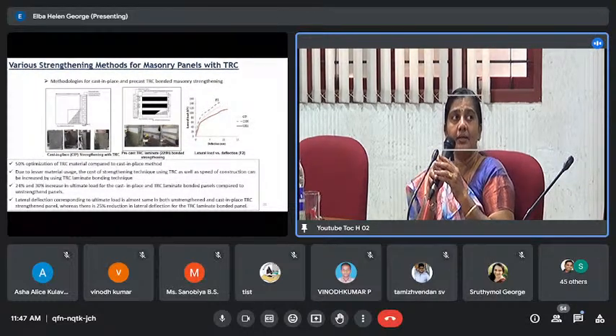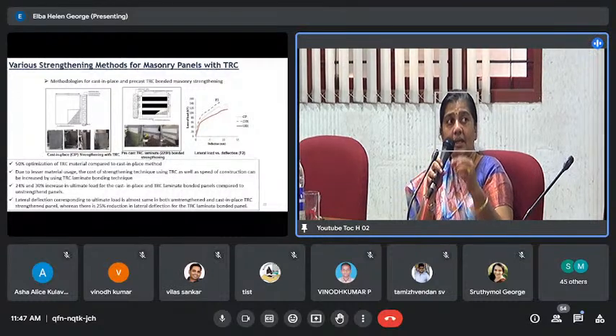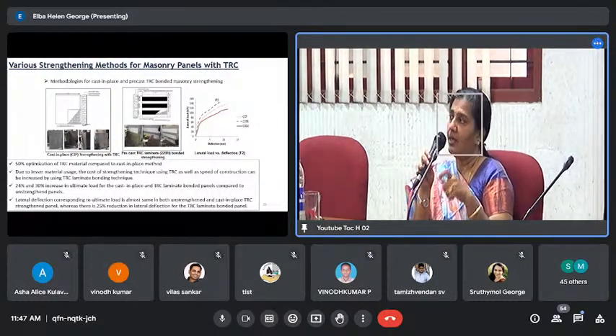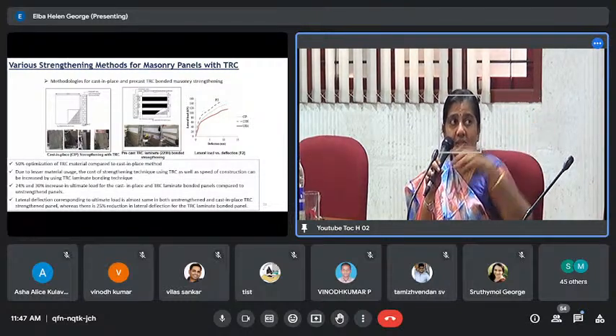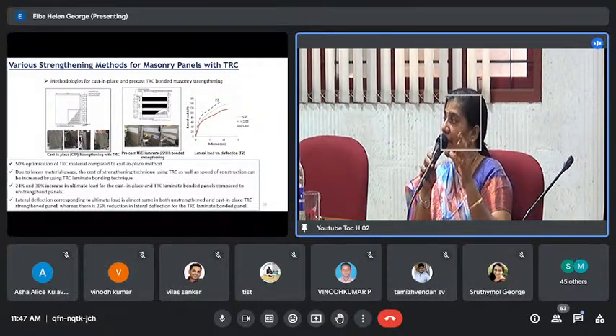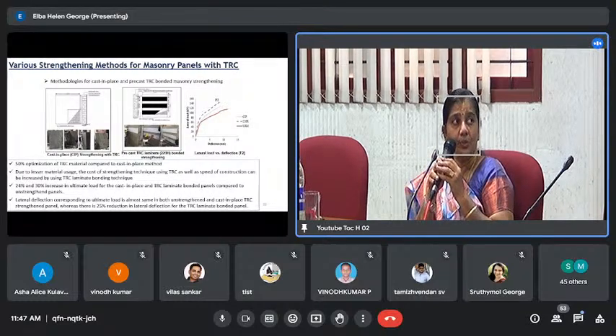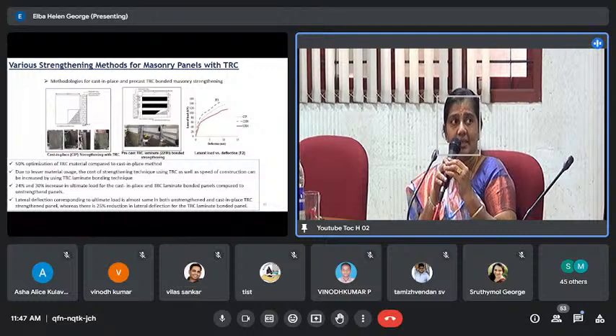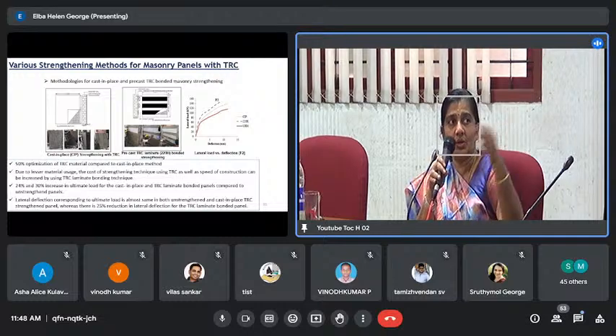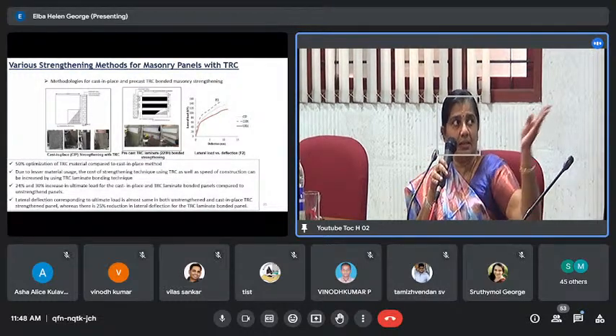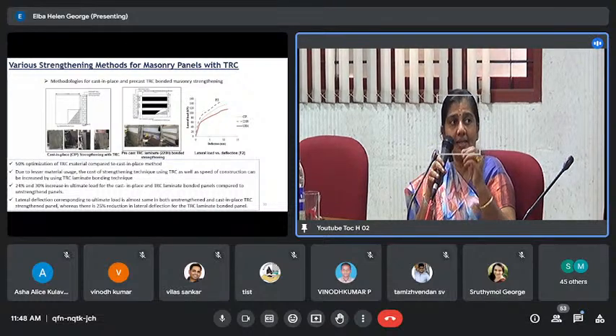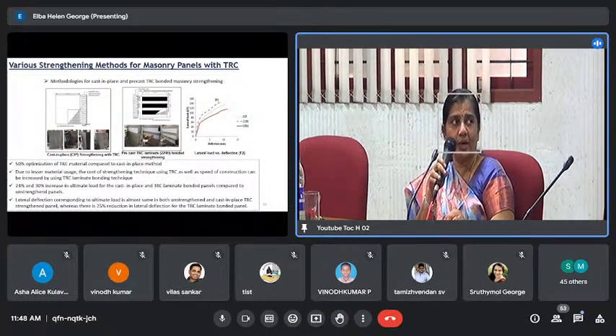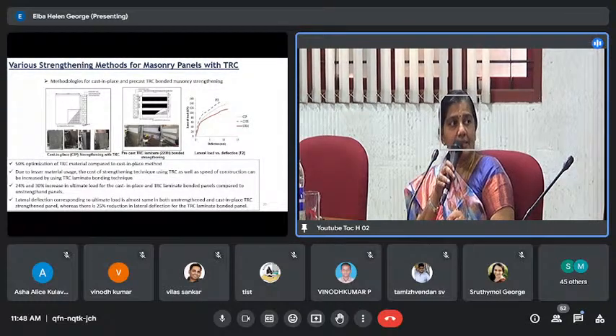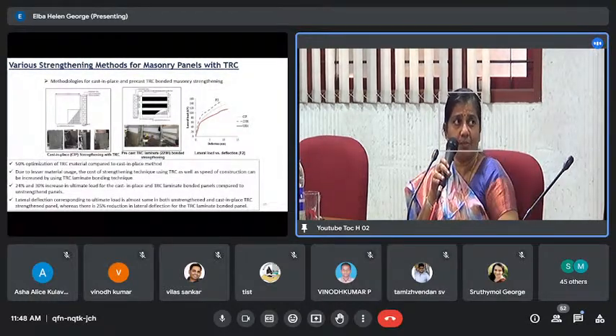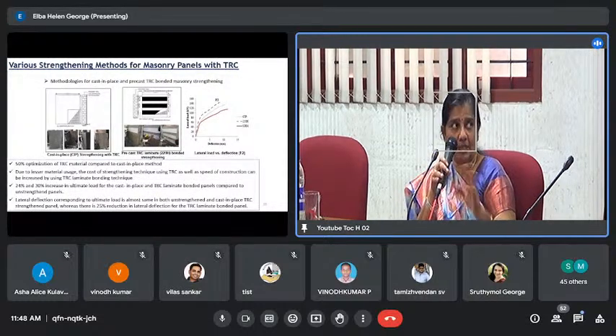Also, you can impart enhancement in strength within the plastering thickness. So instead of the normal plaster, if you have a TRC cast in place strengthening methodology, you can have the panel strengthened using this material. If you do this laminate bonding methodology, we could see that there is 50% optimization of the TRC material compared to the cast in place method, which is shown on the left side. And there is a 24 to 30% increment, and we can design based upon what the enhancement requirement is for these situations. And also there is a comparison between how this precast bonding and cast in place methodology work for this kind of application.